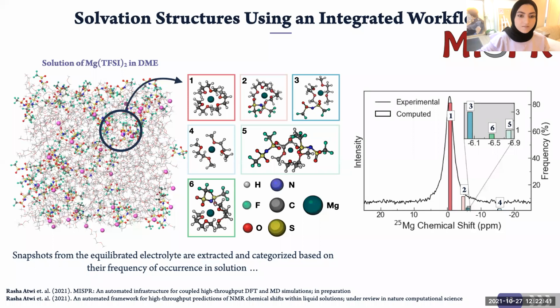And from this approach, we found that the most stable structure identified computationally, number one here, matches very well with the experimental results, with the possibility of the presence of other species in the solution, like number two. And this entire process was automated with minimal interference of the user. And the workflow can be used to study other mixtures as well, not limited to this solution, and other different concentrations, temperatures, and other conditions.